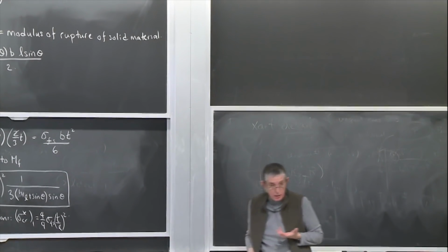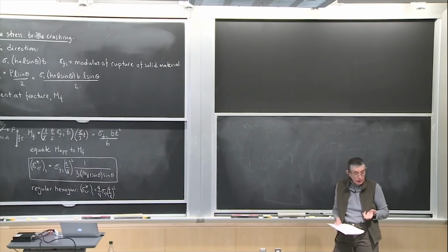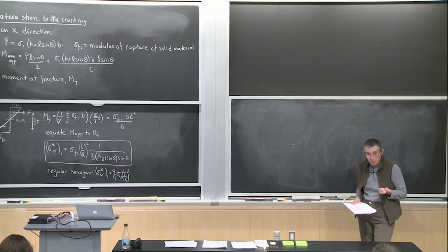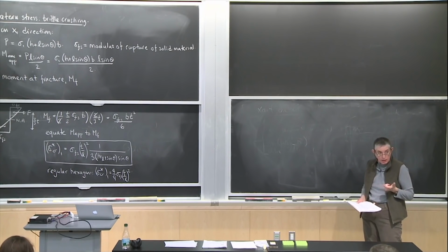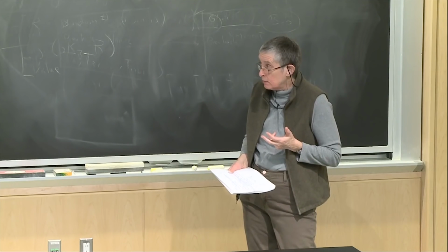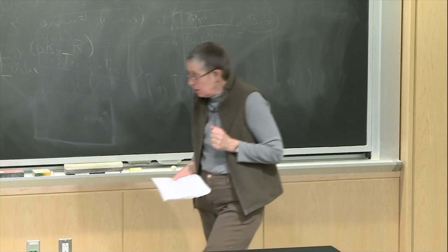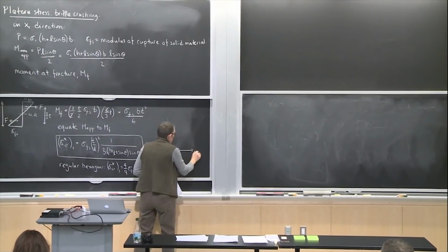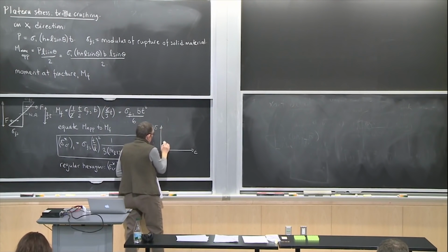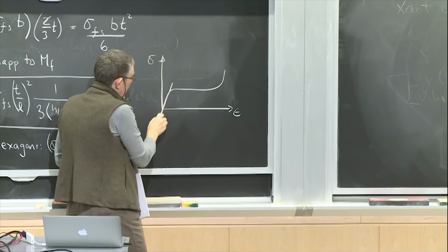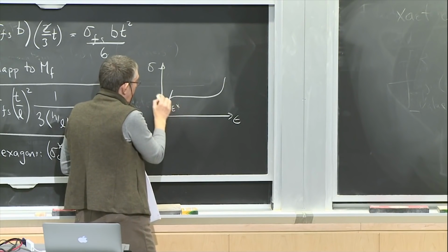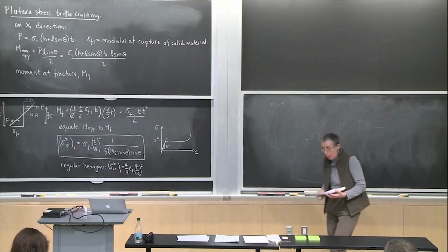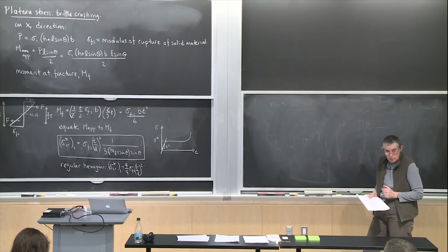So we've got the in-plane compressive properties now. We've got the elastic moduli, and we've got the 3 plateau stresses that correspond to the 3 mechanisms: the elastic buckling failure mechanism, the plastic yielding mechanism, and then the fracture mechanism for brittle crushing. If you think of the stress-strain curve of these materials in compression, the stress-strain curves all look something like that. And now we've figured out equations that give us the modulus here and our collapse stress there. So we can describe that stress-strain curve. All right, so that's compression.